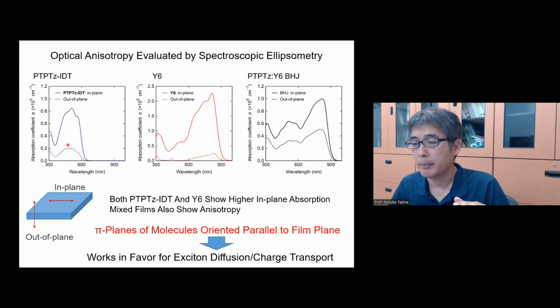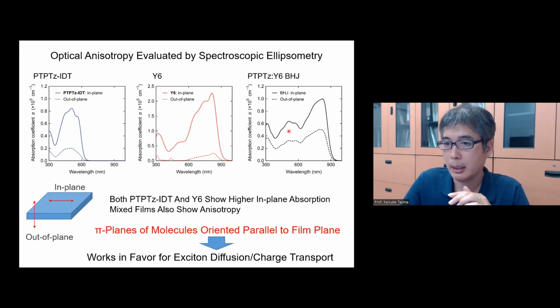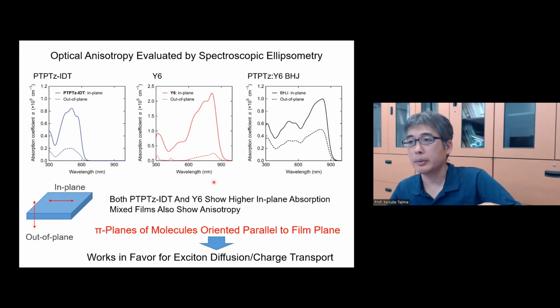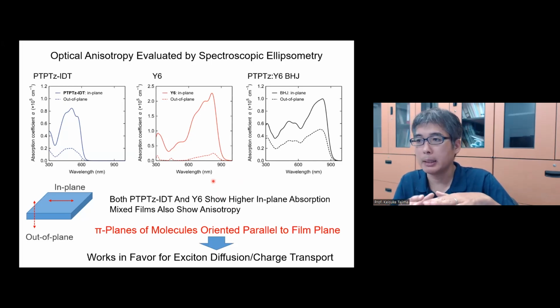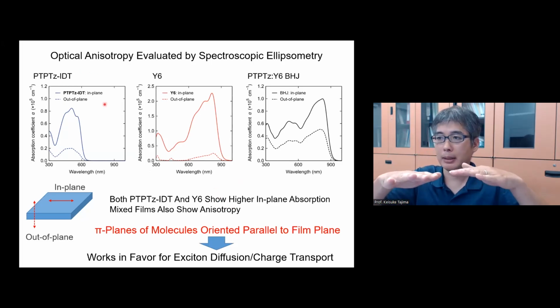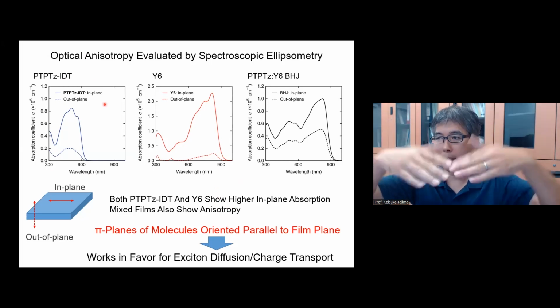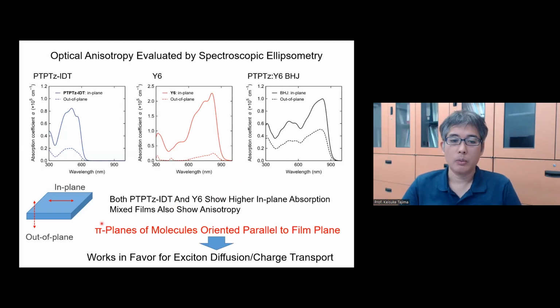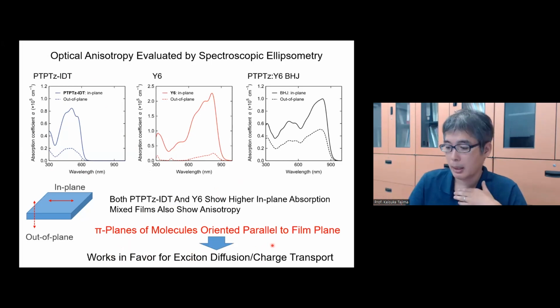This cannot be obtained by the X-ray. The Y6 has a very strong optical anisotropy like this, so in-plane is also very strong. And even in the mixed film, you can see that the bulk heterojunction film has a large absorption in the in-plane direction. So it's a face-on orientation, with the molecules oriented parallel to the film plane. And we believe that this is helped by the shape of the molecule, especially the polymer chain. So, zigzag shape, you can imagine that this one is more stable with this orientation than this way. Okay? So this should work in favor of exciton diffusion and charge transport if you have a face-on orientation in the bulk heterojunction.